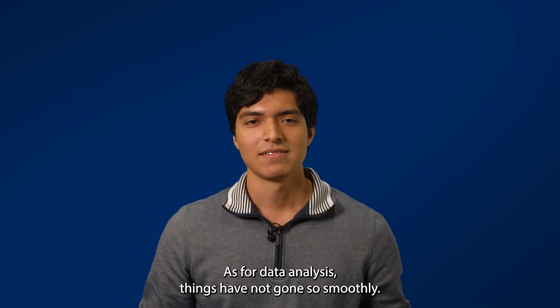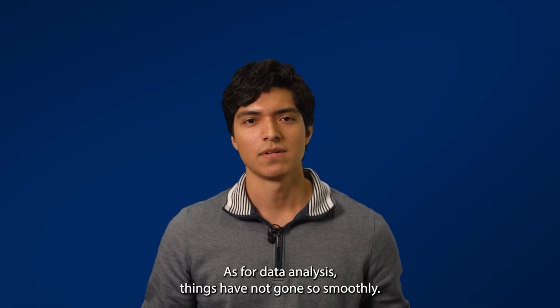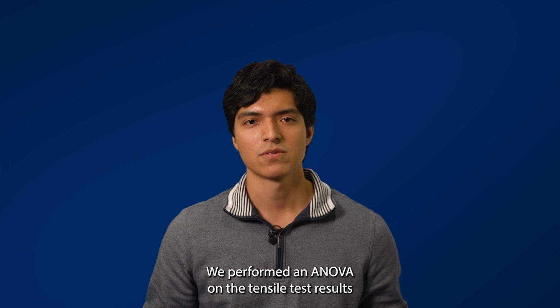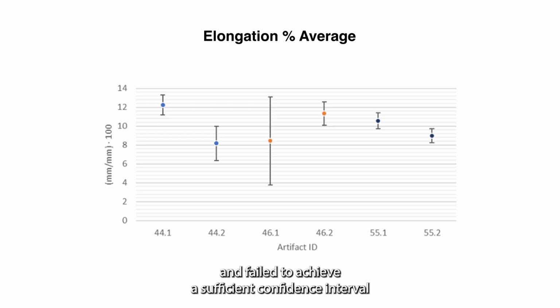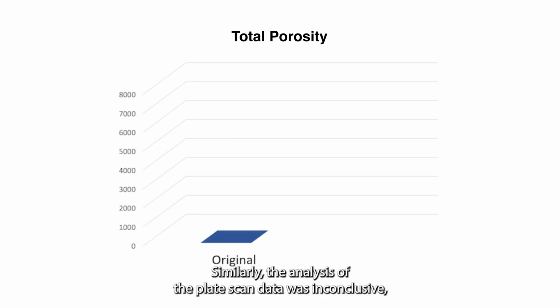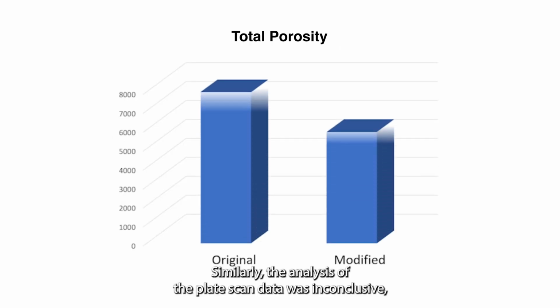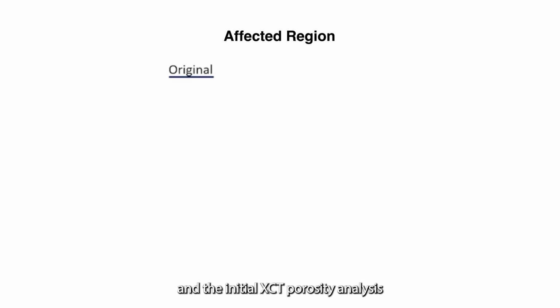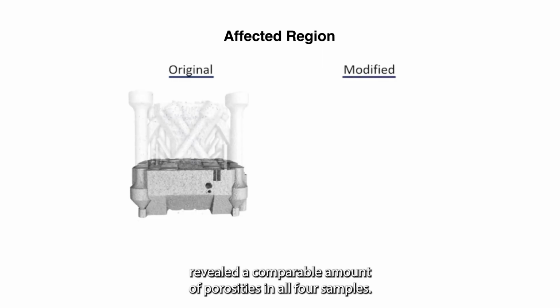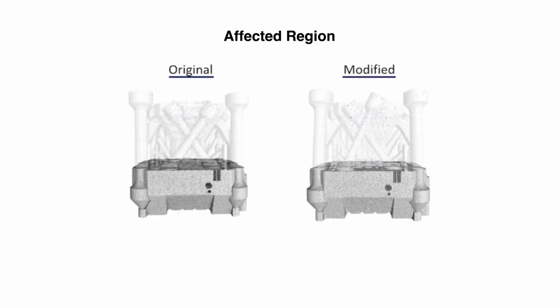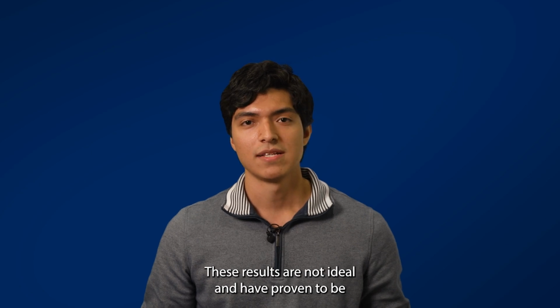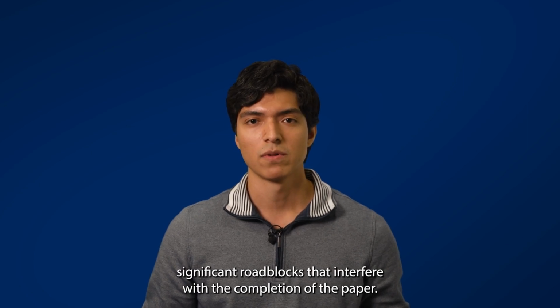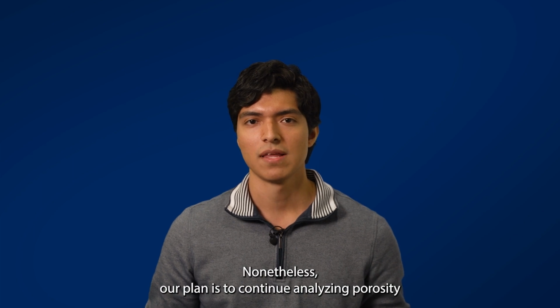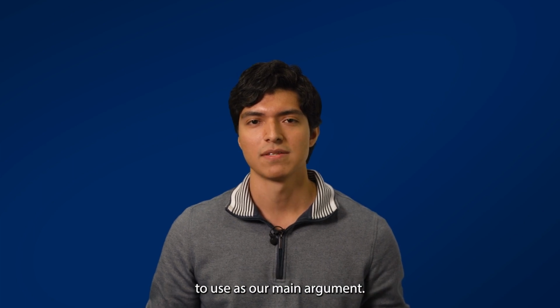As for data analysis, things have not gone so smoothly. We performed an ANOVA on the tensile test results and failed to achieve a sufficient confidence interval to claim that the samples were statistically different. Similarly, the analysis of the plate scan data was inconclusive, and the initial XCT porosity analysis revealed a comparable amount of porosities in all 4 samples. These results are not ideal and have proven to be significant roadblocks that interfere with the completion of the paper. Nonetheless, our plan is to continue analyzing porosity to use as our main argument.